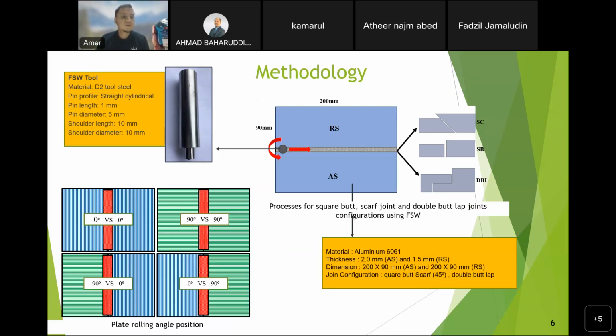For the friction stir welding tool, I'm using D2 tool steel, and the shape of the pin is straight cylindrical. The pin length is 1 mm, pin diameter 5 mm, shoulder length 10 mm, shoulder diameter 10 mm.